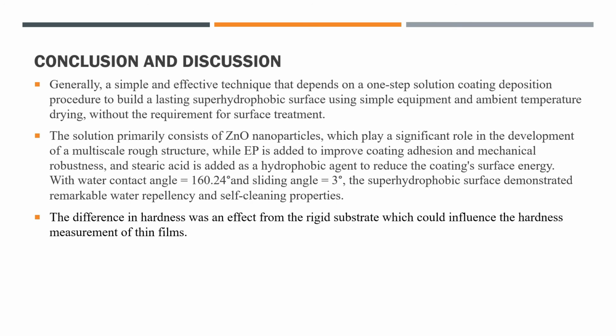The difference in hardness was an effect from the rigid substrate, which could influence the hardness measurement of thin films. Another possible reason for the softness of thick films was the greater amount of solvents retained in the thicker coatings. In general, as the solvent evaporation rate drops at the later stage of film formation, a small amount of solvent can eventually be trapped in the coating for months or years. Several other effects can also take place in thicker films, including the increase in internal stress, the porous structure, and the cohesive failure. Thicker coatings have higher internal stress built up than thinner ones.